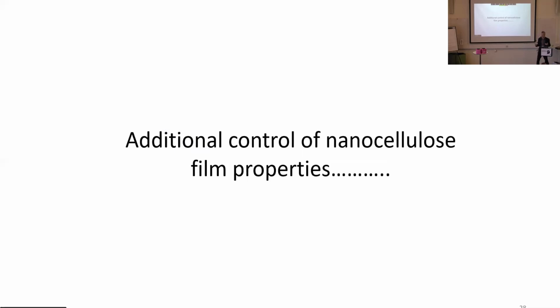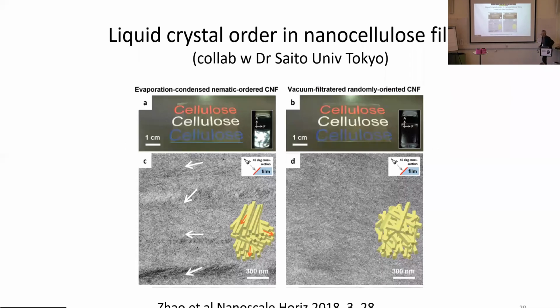So basically, when you cast a film from nanocellulose, usually you think about high productivity, so you do it fast, and you end up with a structure that is not very well organized. You have your fibrils random in the plane. But what my colleagues in Tokyo did was that they let this take time. They did very slow solidification. And then you end up with liquid crystal order in your nanocellulose film.